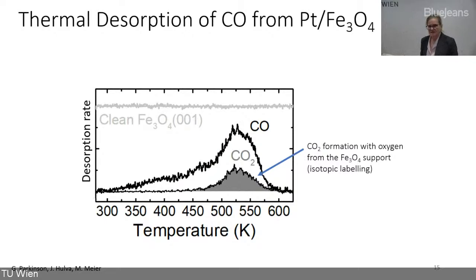These other traces are when you put just a little bit of single platinum atoms. You can see CO desorbs at a certain temperature, but not only CO - also CO2. So the CO reacts and makes carbon dioxide, taking an oxygen from the lattice. That's called the Mars-van Krevelen mechanism. We know that from isotopic labeling.